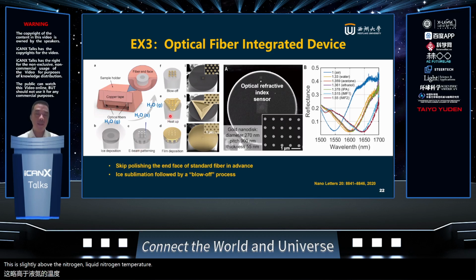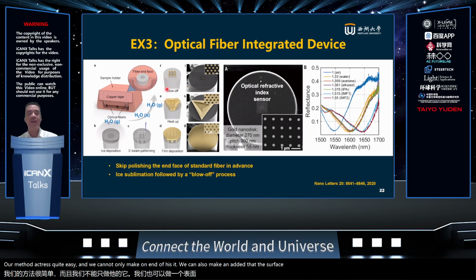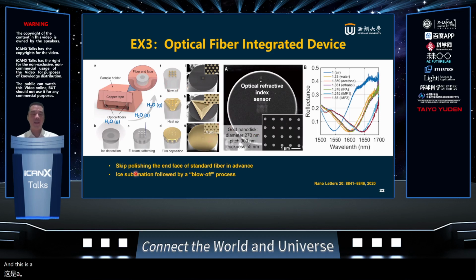By carefully designing a stage, we can make devices on the fiber end facets. And our method is actually quite easy. We can not only make devices on the end facet, we can also make them on the surface of the fibers, as shown earlier. And we can even take away the ice using a simple blow-off process using nitrogen gas. And this is a paper we published two years ago.